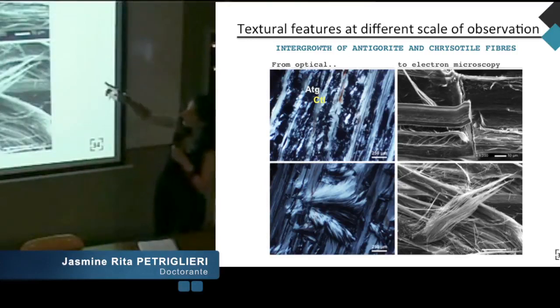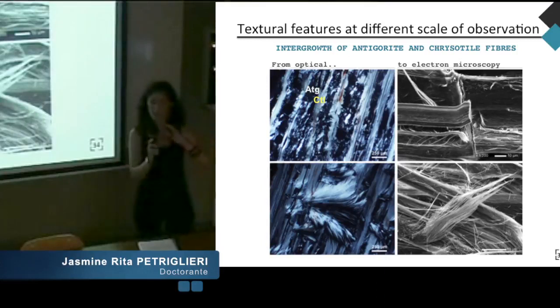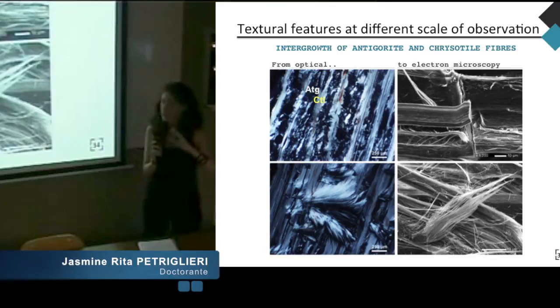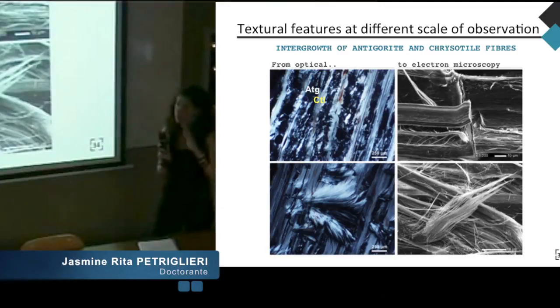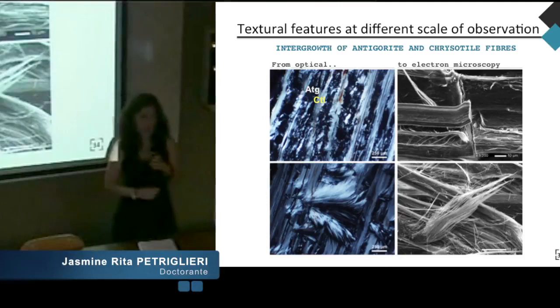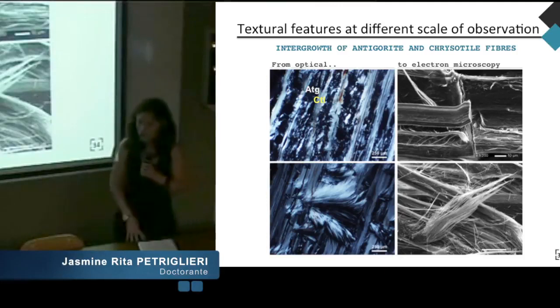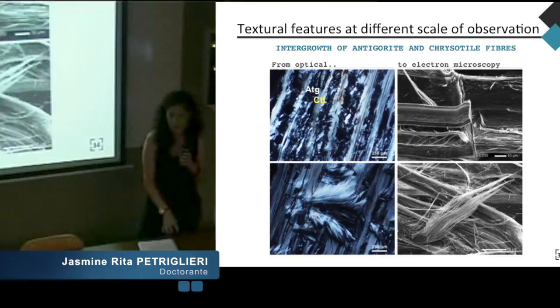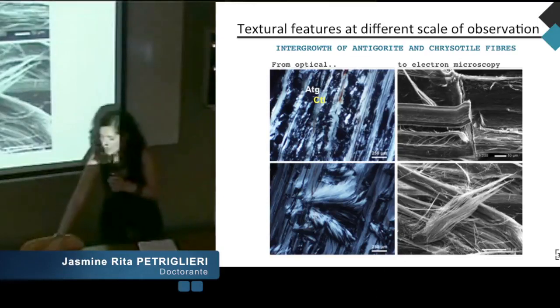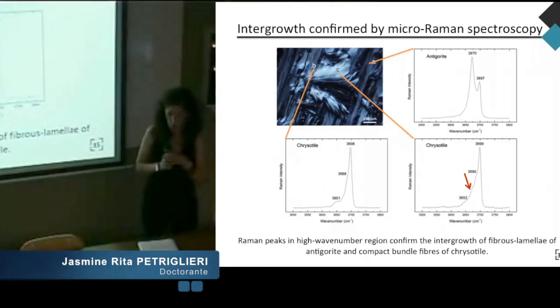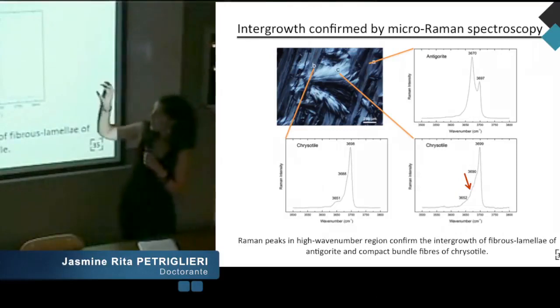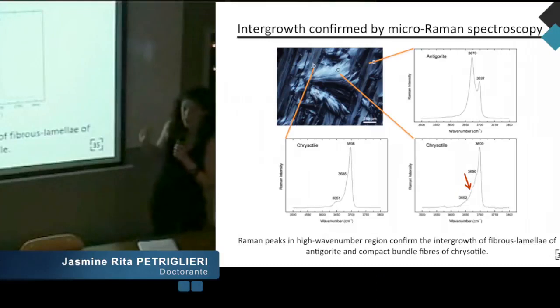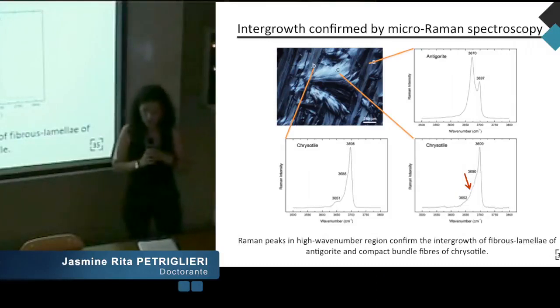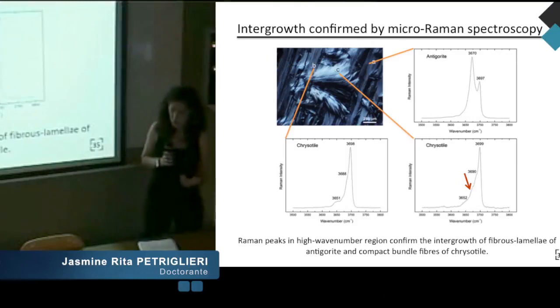It is clear in the figure on the left that there is an alternation of antigorite and chrysotile bundles and lamellae. But to verify this observation, we need a greater degree of detail. For this, we use micro-Raman spectroscopy, pointing the laser beam at the different lamellae and bundles. And the Raman peaks in the high-wavenumber region confirm this intergrowth of fibrolamellae of antigorite and compact bundles of chrysotile.